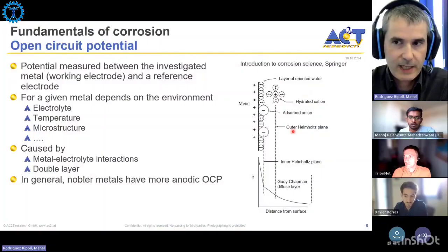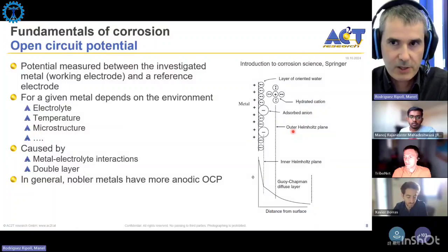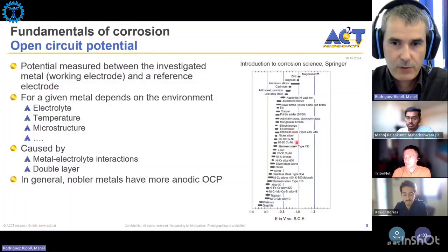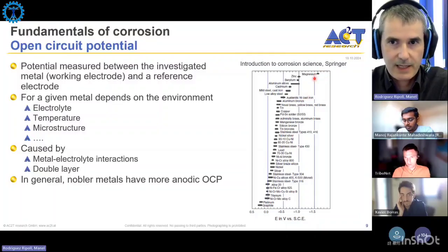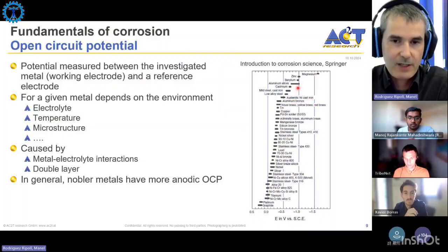And what we can also learn from this open circuit potential is that in general, a noble metal, when we say a metal is not corroding, is because the open circuit potential is typically more anodic, so it's higher. This will be here, for example, the case of platinum with a very high corrosion potential. And the metals that are less noble, for example, magnesium, is a metal that reacts very quickly in aqueous media, so this has a very cathodic open circuit potential. And when you combine these two metals, you build a galvanic coupling, and then the metal with the less noble potential is the one that will corrode. So basically, it will act as an anode and will protect the other metal from corrosion.